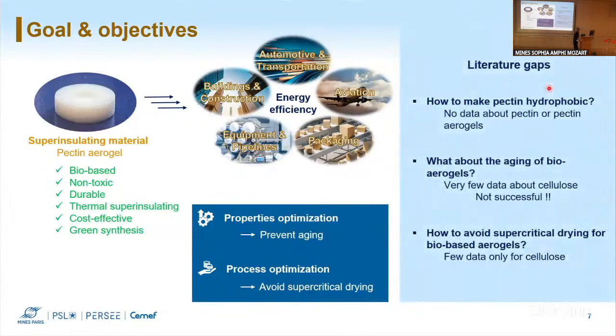When I started my thesis, we had a very big gap in the literature considering this topic. In general, for pectin hydrophobization, there are practically no works. There are some modifications, still not allowed, but nowhere is hydrophobicity of aerogels or pectin itself mentioned. Then there are no data about aging of bioaerogels. In a few publications, some people mention 1 day of aging, and it was never successful to keep the properties. And for avoiding supercritical drying, we only know for bio-based aerogels one work for cellulose with a specific fabrication process. So we needed to start from this.